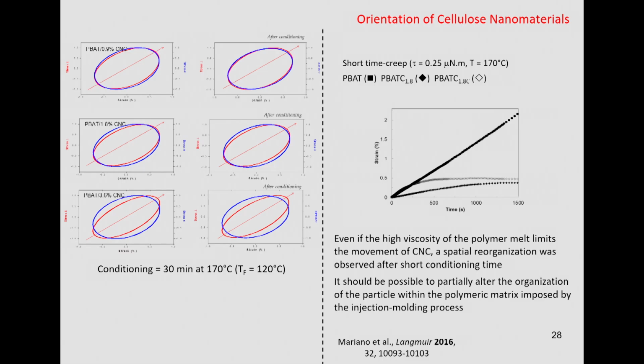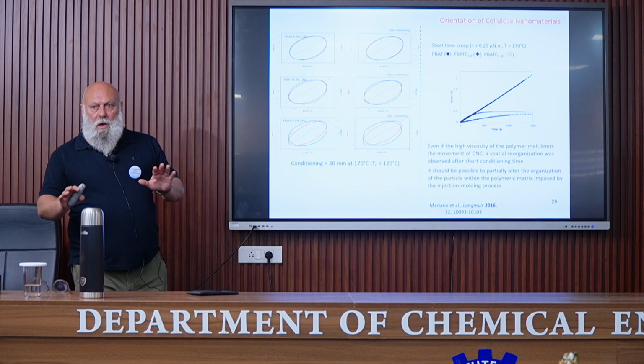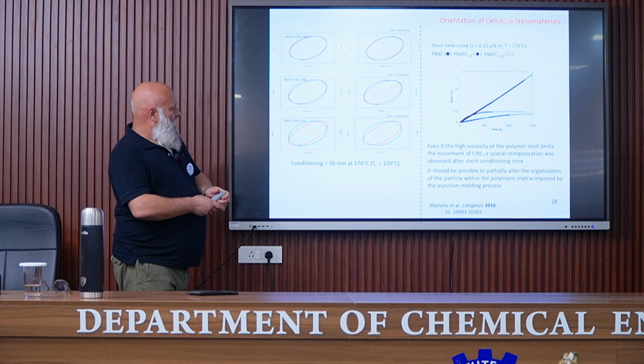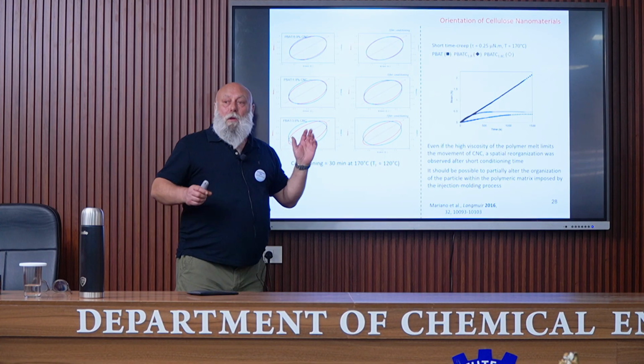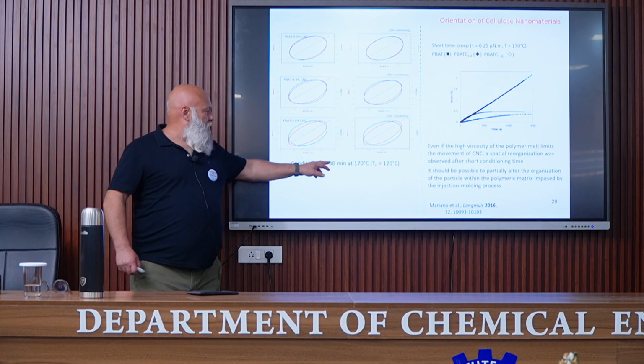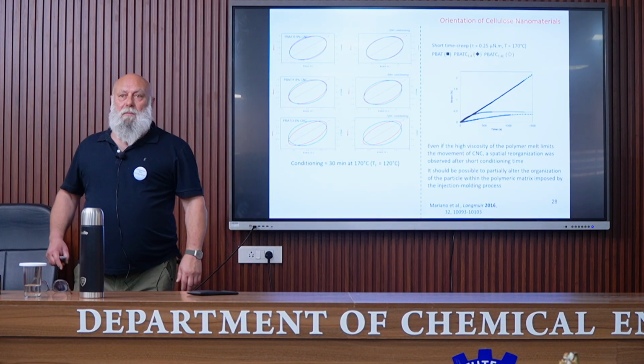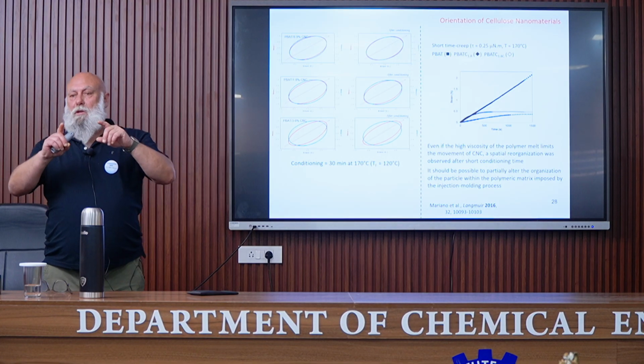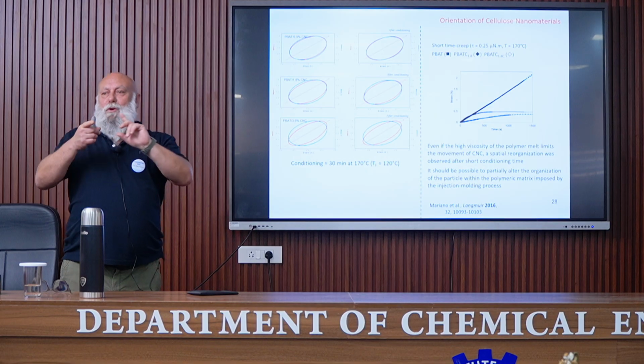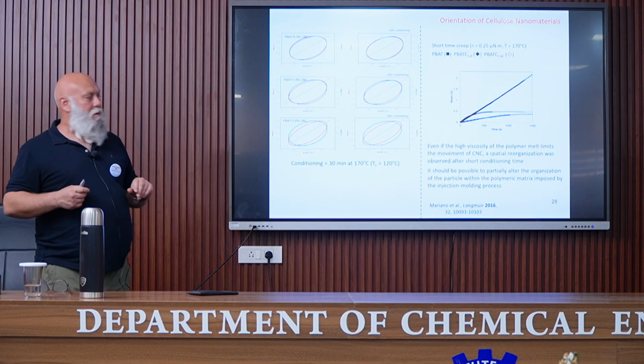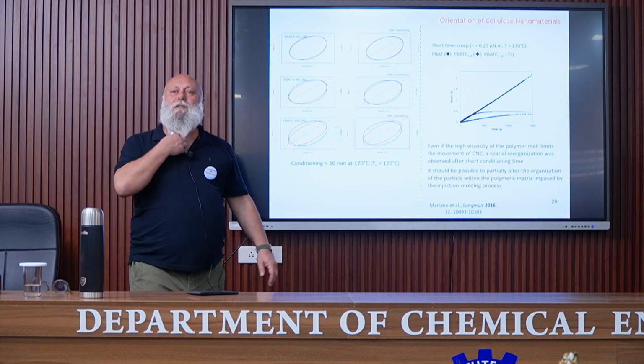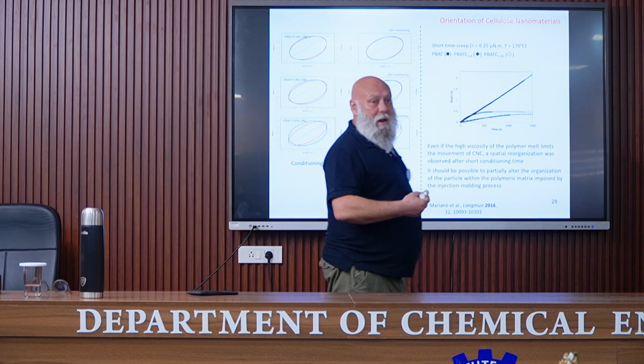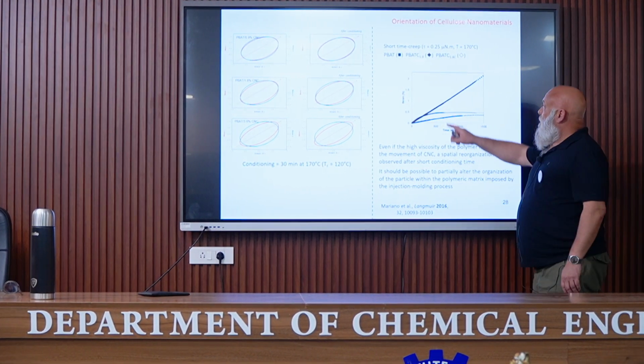And what we try is to condition the material at high temperature, 170 degrees, so it's higher than the melting point of PBAT, during 30 minutes, and so we are sure that no degradation occurs, and we perform again the experiment. Not so much difference. What we expect with this thermal treatment is maybe that we can destroy the orientation of the nanocrystals and maybe recover the formation of the percolated network. But we didn't think too much because the polymer melt is highly viscous. But there are some differences.